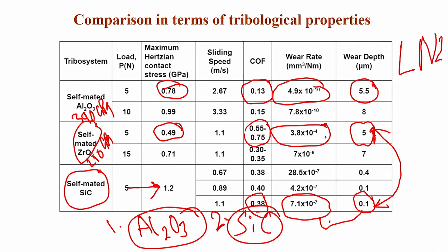The reason I provided while explaining these intriguing observations was that in the transformation from tetragonal zirconia to monoclinic zirconia, the intermediate product is orthorhombic zirconia. Since we are doing these experiments for a relatively short time, 10 minutes or so, we are not giving enough time for the system to come back to the equilibrium phase, that is monoclinic zirconia, and therefore orthorhombic zirconia forms. And in the case of alumina, the thermal conductivity effect is also very important, and we have seen the occurrence of both intergranular and transgranular fracture, cleavage steps and so on, and that leads to wear of self-mated alumina as well.